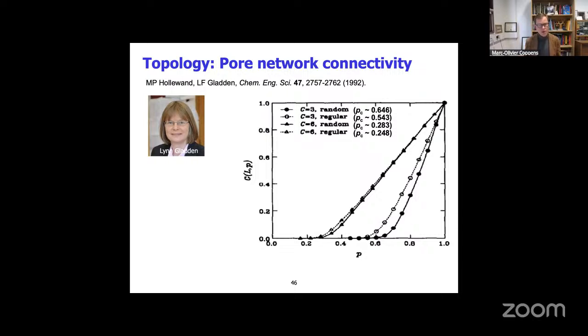You can find out, is it important to include this connectivity? Is it not important? When does it become important? Is it important that the pore networks are regular? Or should I really include the randomness of these pore networks? That's what they actually were testing here. And so what you see here is the conductivity. So it's like a diffusivity, okay, of this pore network as a function of the probability p that, say, a pore is, so if you have a lattice model where two nodes in this lattice are connected or not.